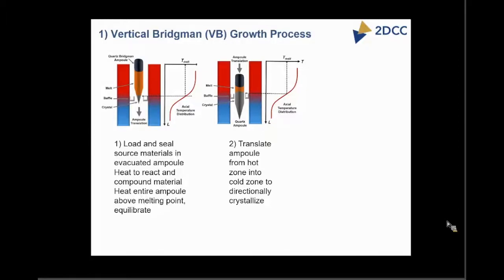So you translate it to directionally crystallize the material. There's a couple of ways you can do this too to start. Often, when you're looking at larger crystal growth efforts, you'll use a seed crystal, partially melt it back, and then solidify off of that to set the crystallographic orientation and assure monocrystalline growth. Or you can self-seed either with a tapered seed structure shown in this schematic, or with a constrictive region, a pinch region, so that you select a single grain and then grow that out to try and optimize the structure of the grain.